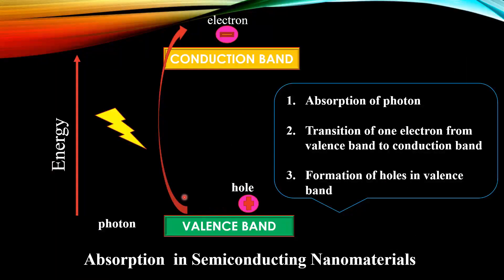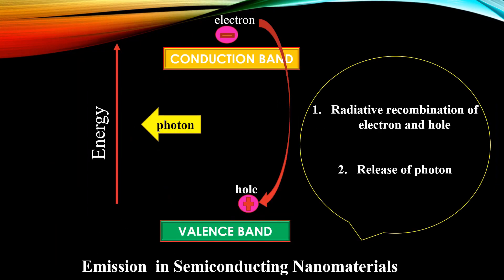This is how it works. The first step: a photon is absorbed by the material according to its band gap, by which the electron is transferred from the valence band to the conduction band, generating a positive counterpart known as a hole. In the next step, when the electron relaxes back from the conduction band to the valence band and recombines with the hole, it generates a photon of the same energy as the corresponding semiconductor band gap. This is how semiconductor nanomaterials generate photoluminescence.